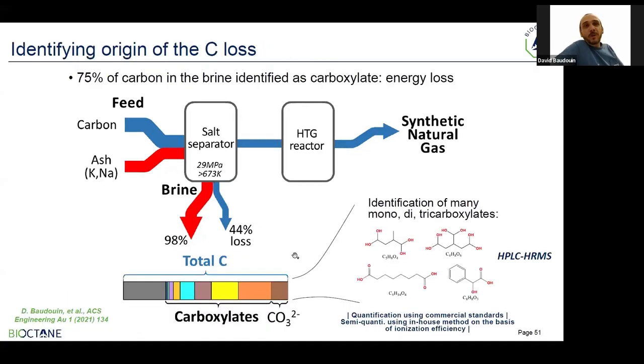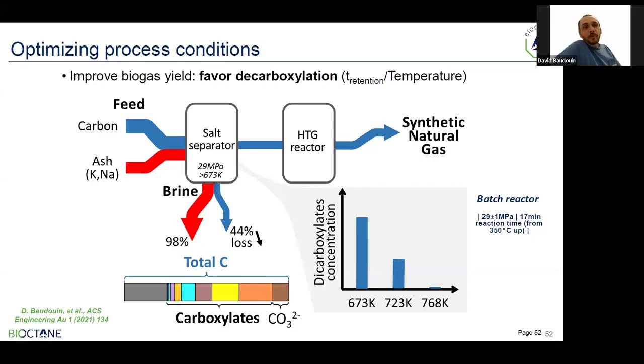So to make a very long story short, we performed a deep investigation, and we quantified that the carbon present in the brine was up to 2/3 composed of carboxylates, and probably more of it was also organics, not identified. And we were able to optimize the process by simply increasing the temperature in the salt separator to favor decarboxylation of these organic compounds, which will lead to, of course, more CO2, but more organic matter that will not be separated along with the brine, and that will end up in the catalytic reactor, and will then be further converted into gas.